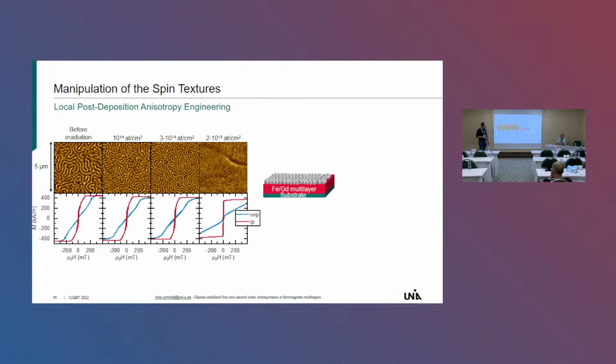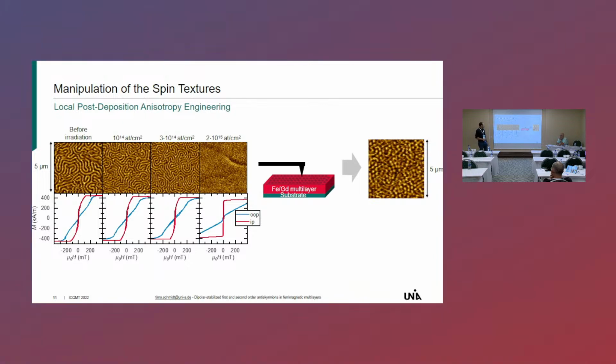And so we can remove the nanospheres and then look at it with the MFM, and we really see some round objects here, almost in a hexagonal lattice. It gets a little bit confusing around here, but there are areas where you can really see that hexagonal lattice from the nanospheres. Looks like it's working really well, but there are some problems with this technique.